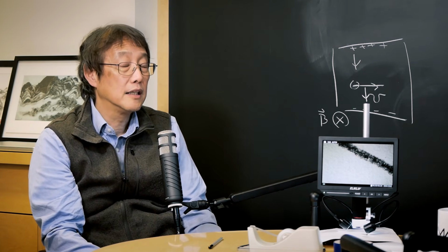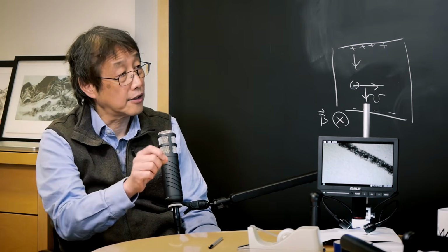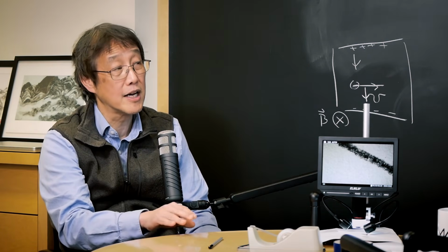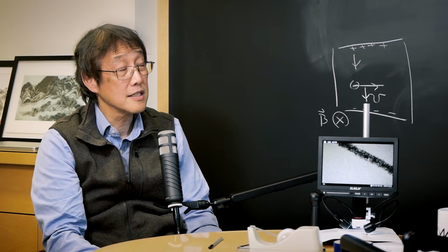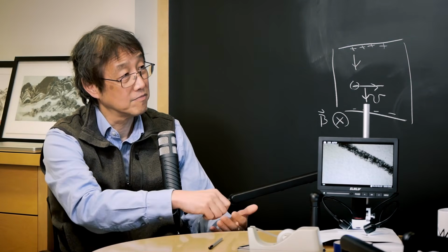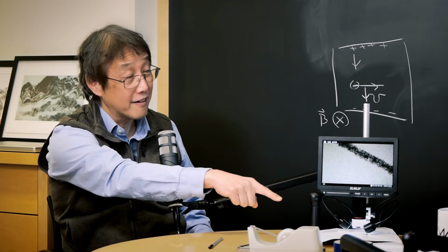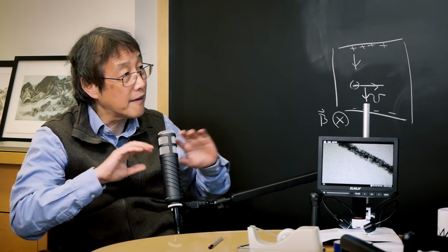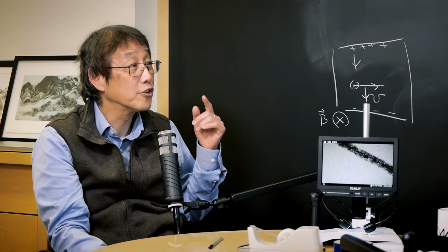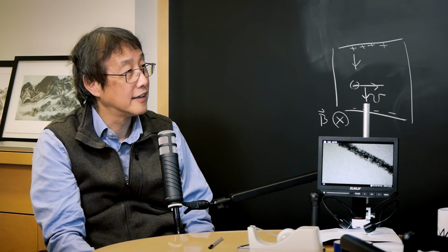We immediately understood the advantage of the Scotch tape. Part of the reason is that with this nano pencil method, you can cleave, and potentially if you control the adhesion force well, I'm sure eventually you can optimize it to create something very thin. The problem is that this is a really serial method, right? But imagine you have Scotch tape with the graphite crystals, cleave it off and rub it out. There are billions of nano pencils working in parallel, so the cleaving efficiency is extremely high. The only downside is there is a lot of junk, a lot of thick crystals. How to find the thin crystal? That's the important part, and I think there's also luck factors in there, right?